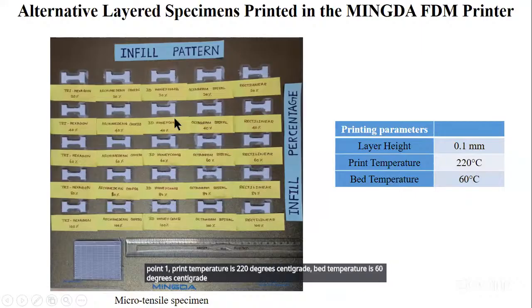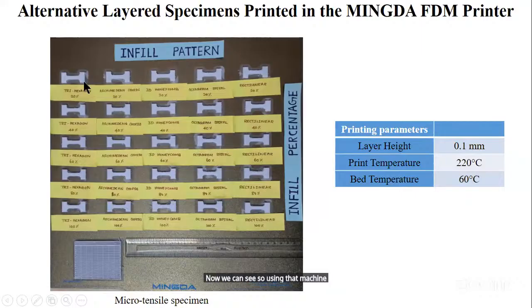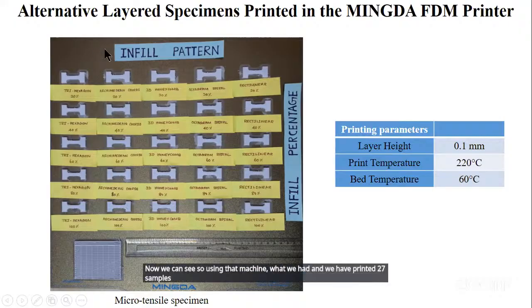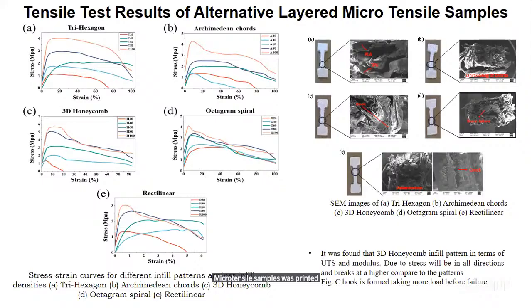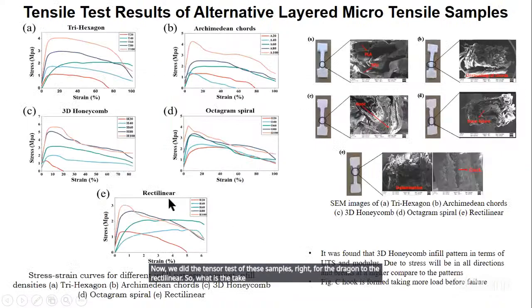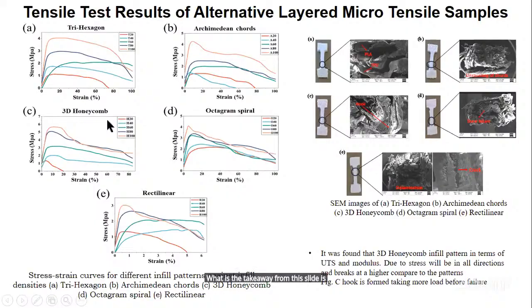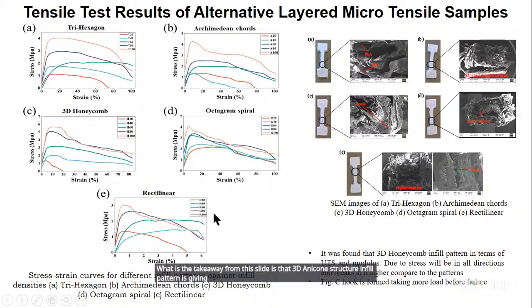Now we can see, using that machine, we have printed 27 samples, that is L27. This is the infill pattern, and you have the infill percentage. The white color you are seeing are the alternative layered micro tensile samples that were printed. Now we did the tensile test of these samples, from the trihexagon to the rectilinear. The takeaway from this slide is that the 3D honeycomb infill pattern is giving better results compared to the other infill patterns.